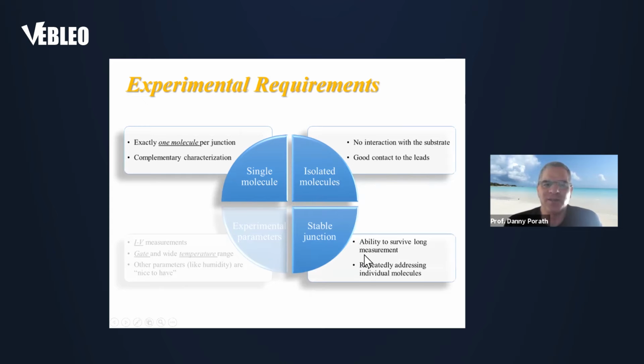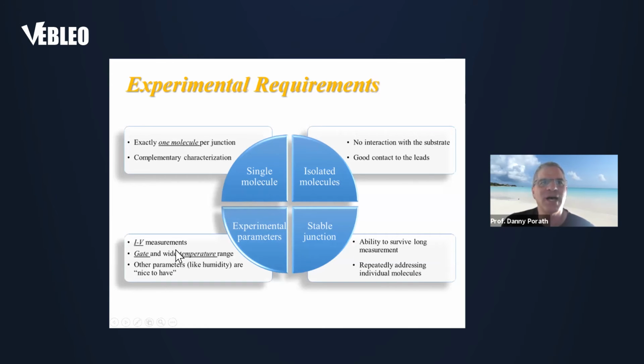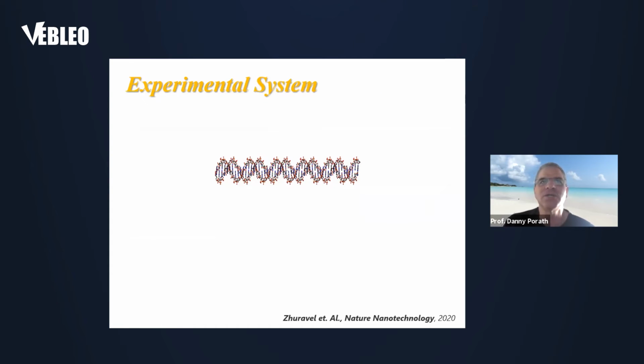So unlike the STM break junctions, where you measure a certain molecule but you cannot really address a specific molecule, we want a molecule that can survive long enough, and we can perform repeated measurements on this molecule. And if we fulfill all these conditions, then we can perform IV measurements, gate and change the temperature, measure the temperature dependence, and we can change other parameters like humidity or the measured sequence, and so on. So that's kind of the requirement for what we term as the reliable and good experiment.